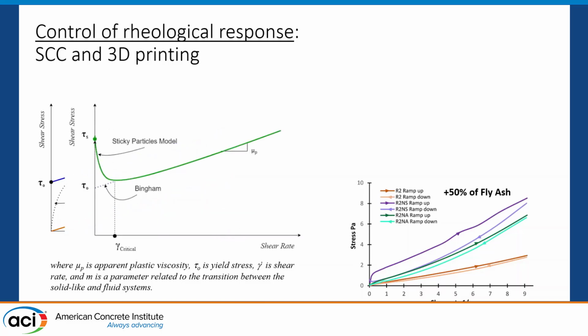But what is the ideal response? Bingham is good, but what happens if we can have a material which has additional stiffening at lower shearing rate? Because when you deposit, your shearing rates are reduced to zero. So if we can have a material with such a rheological response.